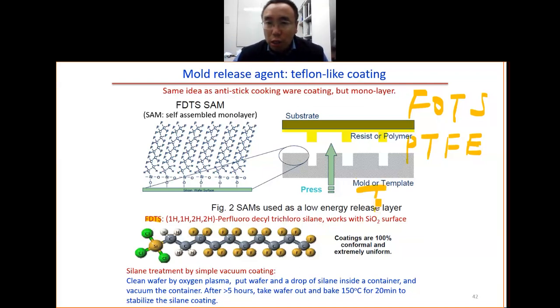This is also called Teflon. But if you coat a layer of Teflon on the wafer surface, this will not work because the Teflon will not adhere to the wafer. So the Teflon film will not adhere to the wafer. So when you do the imprint, it will be peeled off easily. So to solve this problem, on one side, this is like a Teflon, fluorocarbon.